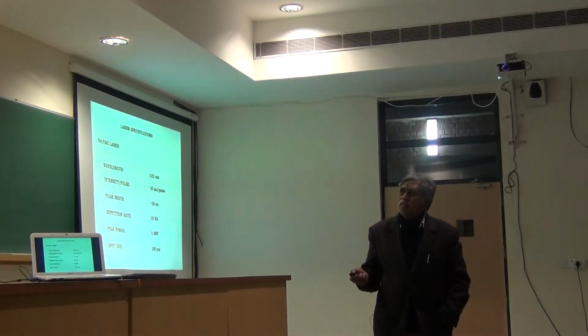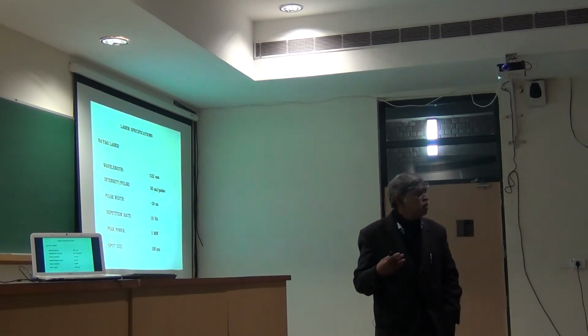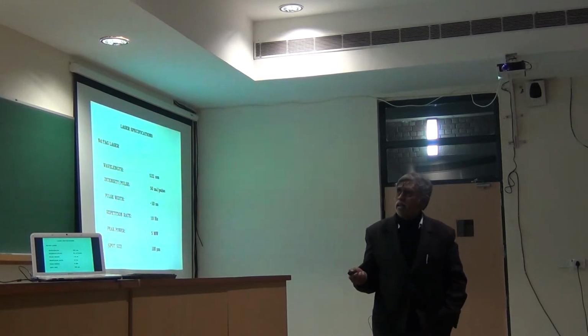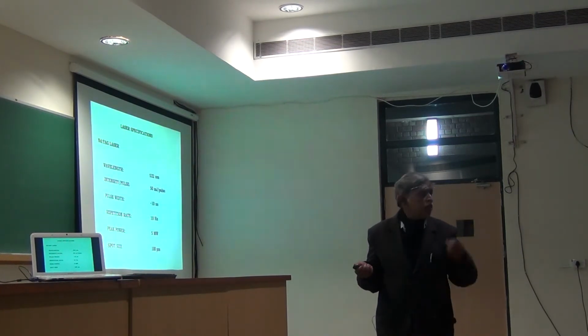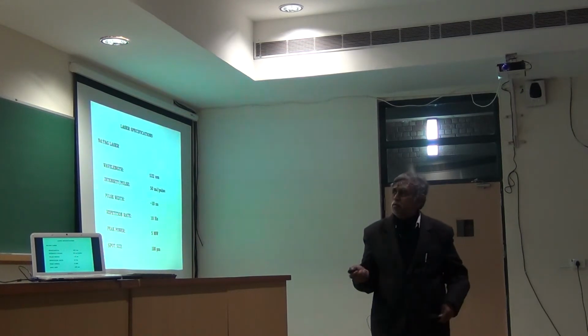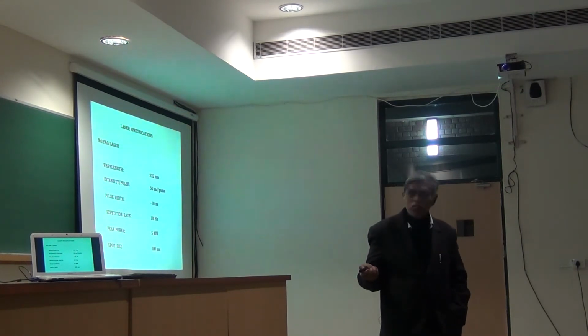The laser that we use, at least, is a neodymium YAG laser with a wavelength of 532 nanometers. It basically lases at the fundamental, which is 1064, which is infrared. But you can take the second harmonic, which is 532 nanometers. The intensity is roughly around 50 millijoules per pulse. The pulse was about 10 nanoseconds, and it hit at 10 hertz, so it sort of hits you 10 times a second. And the peak power, which is the power within the laser pulse itself, is about 5 megawatts, which is enormous. And the spot size is roughly around 100 microns.